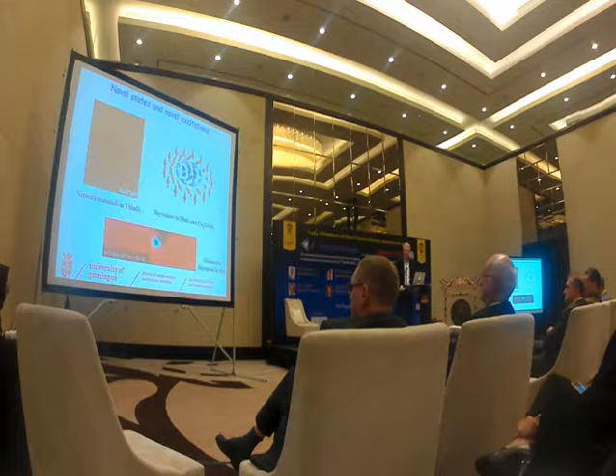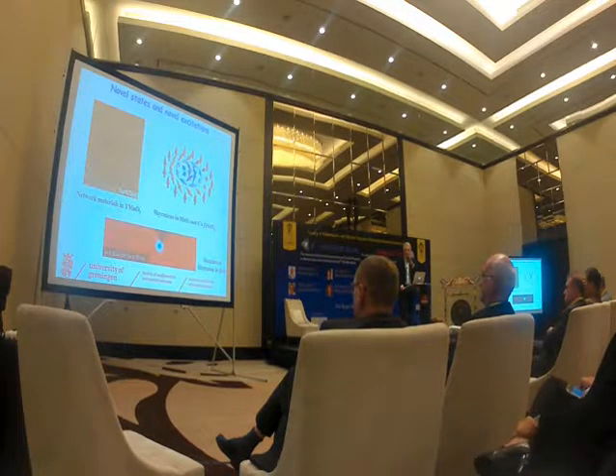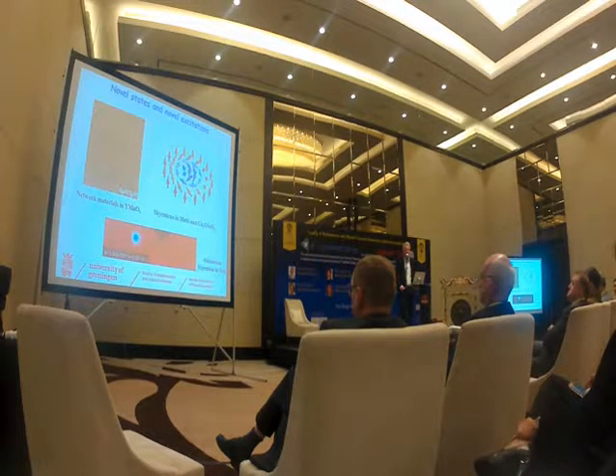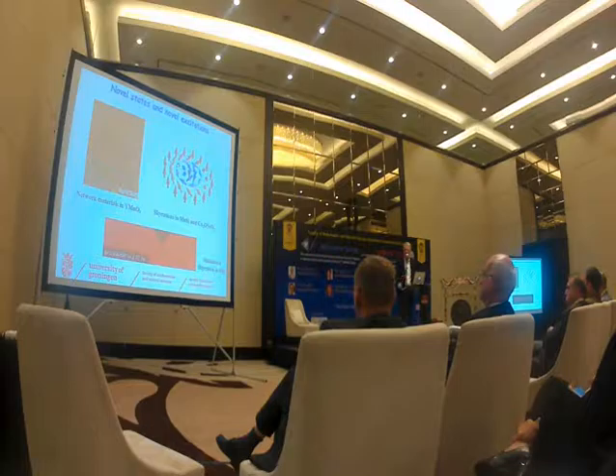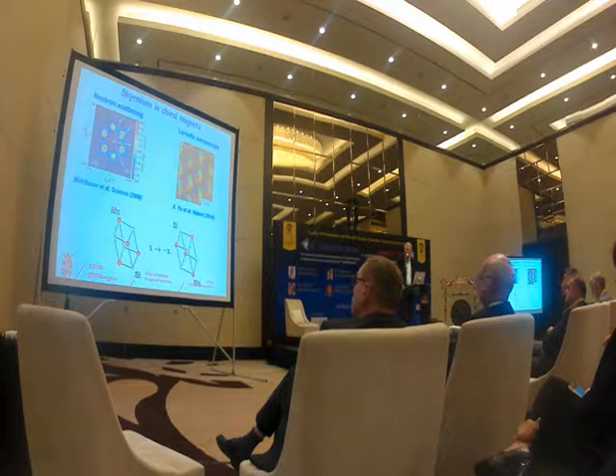where you see this topological excitation move throughout the structure without any dissipation. So basically, you do not move a single spin, because a single spin would mean that you would also have to move its charge. But you move this as a collective excitation, and as a collective excitation, it does not dissipate any energy. The materials that you need in order to make these are very special. And the materials that you have to make in order to make these are materials that lack inversion symmetry. Inversion symmetry breaking materials are very rare, and there are only two known to us at the present moment.